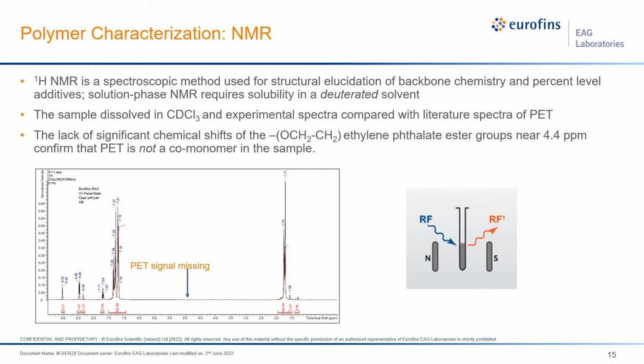It's a solution phase technique, which means that we need to be able to dissolve our sample. And for NMR, we need to use a deuterated solvent so it doesn't create additional signals in the sample. Using the information that we gained from FTIR spectroscopy, we're able to look up materials that can be dissolved with an appropriate solvent. And for this, we use deuterated chloroform.